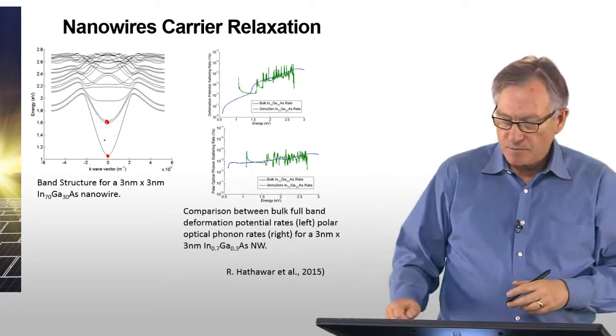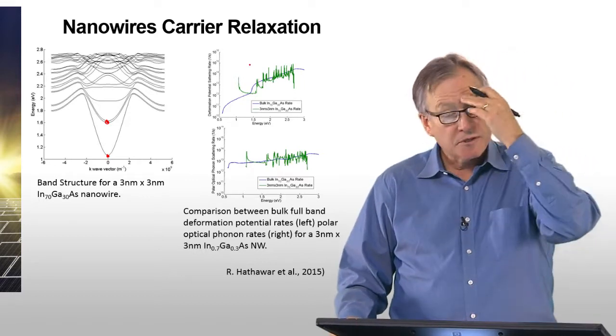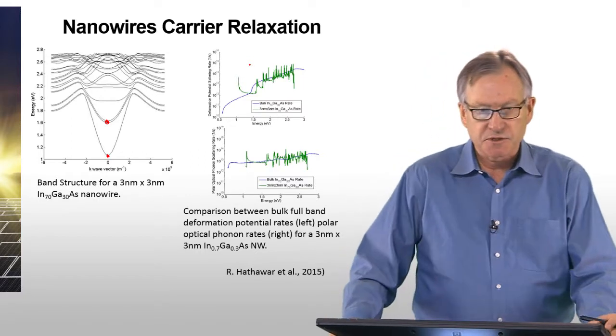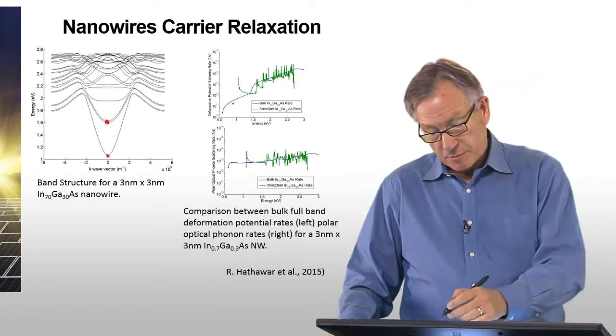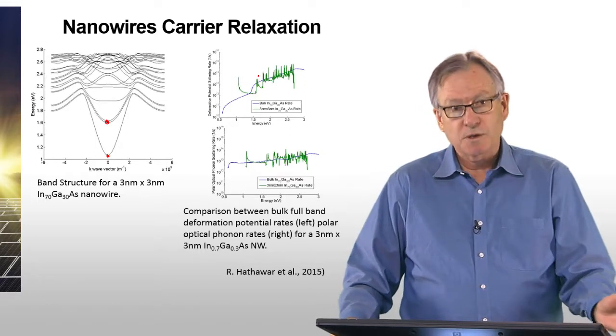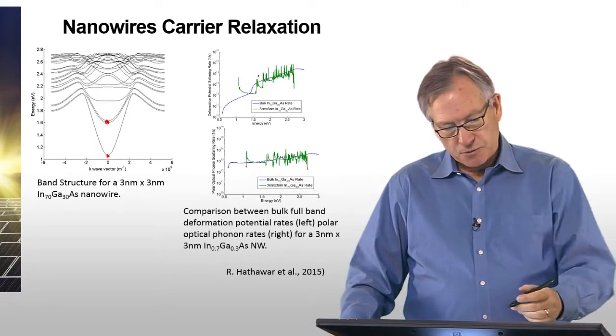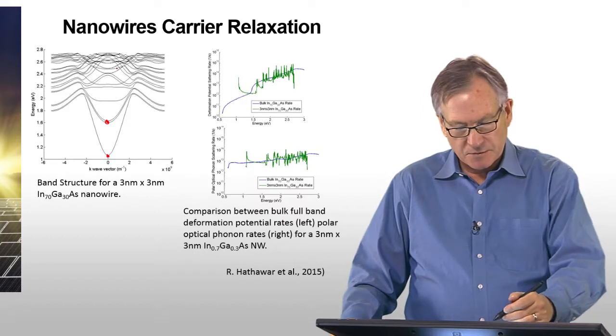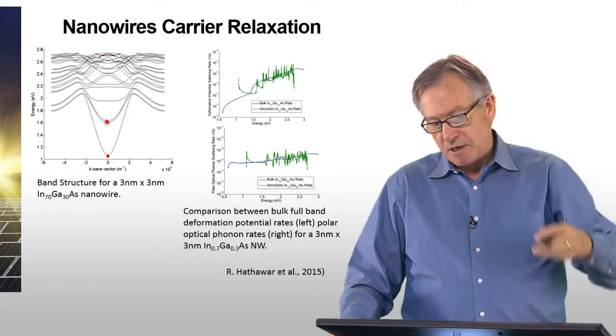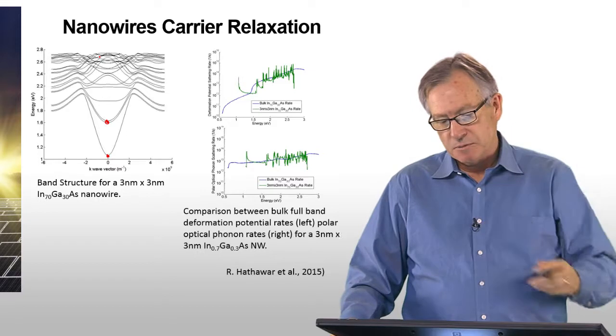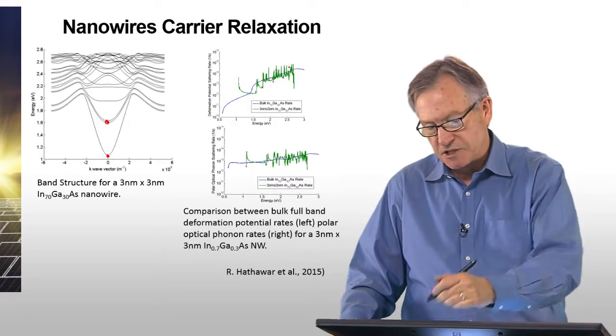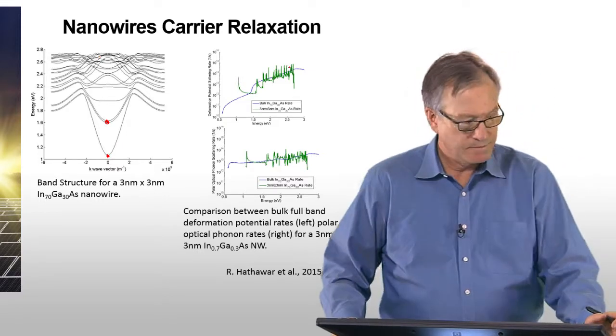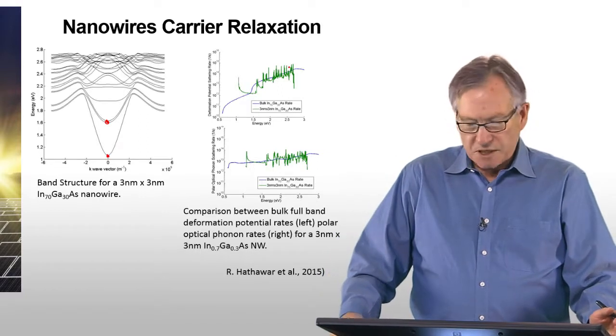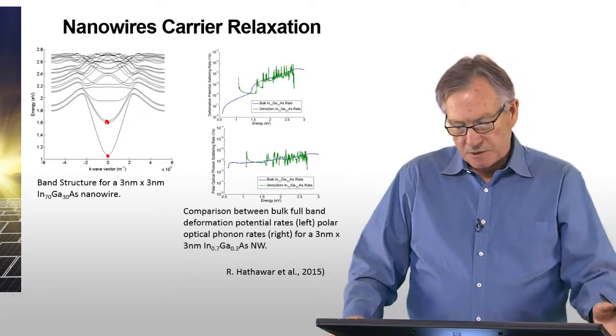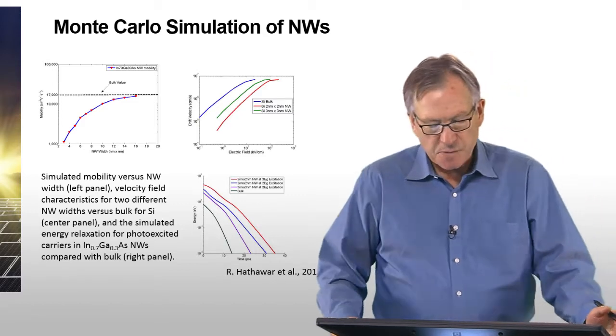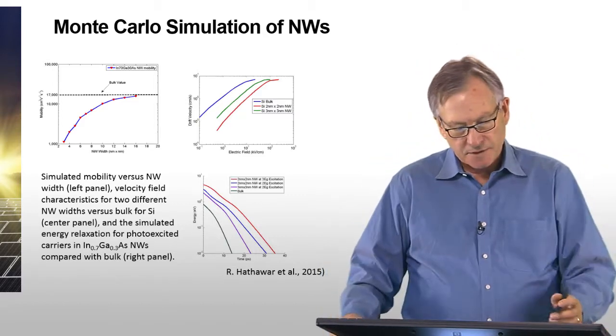What's shown on the right is the calculated scattering rates that are done quantum mechanically based on this band structure, and they're compared to the bulk rate. I showed this before, and it shows that as you go to higher and higher energies, you have many, many levels in the nanowire, and that asymptotically approaches the density of states of the bulk system, and the scattering rates then look like a piecewise continuation of that. So we use those rates in Monte Carlo simulation and look at the relaxation dynamics. These are some of the effects because of the confinement.